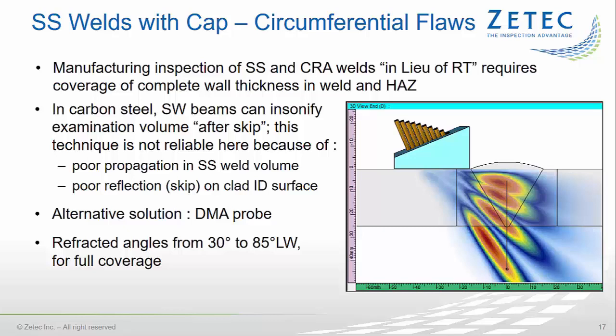We will show how to set up an alternative solution for the detection and sizing of circumferential flaws using a Zetec standard DMA probe at 2.25 MHz with refracted L-wave angles from 30 to 85 degrees for full coverage of the examination volume without skip.